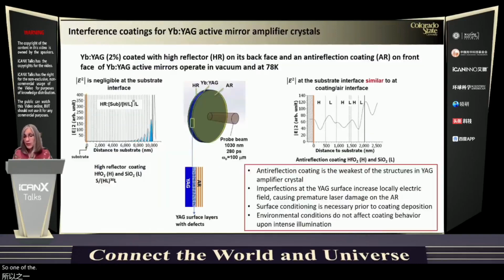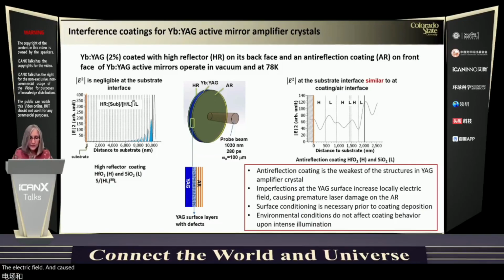So one of the examples of the work that we have done is we have investigated the performance of anti-reflection coatings and high reflectance coatings in active mirror amplifiers for the ytterbium YAG. And here what we learned is actually that we not only have to make good coatings, but we also have to condition the interface between the coating and the crystal, because at the interface there are defects that actually will intensify the electric field and cause damage.